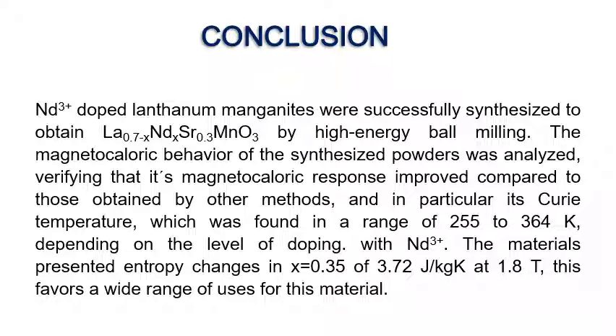In conclusion, neodymium-doped manganites were successfully synthesized to obtain lanthanum strontium manganite by high-energy ball milling. The magnetocaloric behavior of the synthesized powder was analyzed to verify that the magnetocaloric response improved compared to that obtained by other methods, and in particular its Curie temperature, which was found in a range between 255 and 364 Kelvin, depending on the level of doping with neodymium. The materials presented an entropy change of 3.72 joules per kilogram Kelvin at x equals 0.35, at 1.8 Teslas. This favors a wide range of uses for these materials.